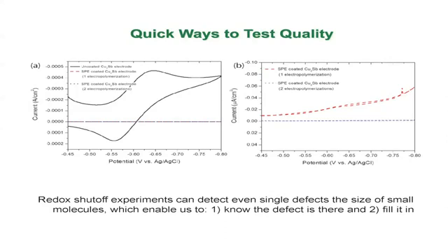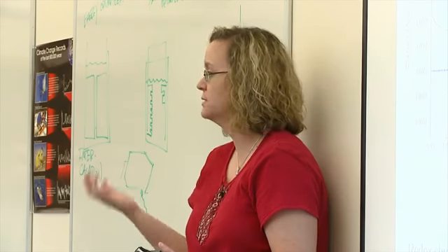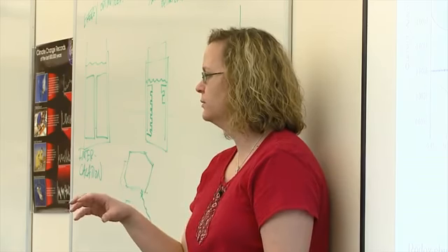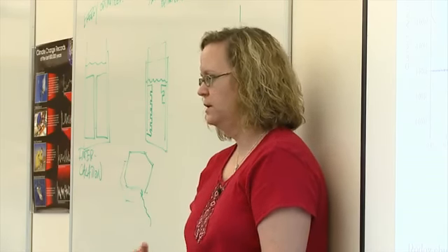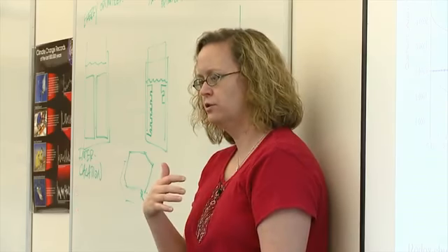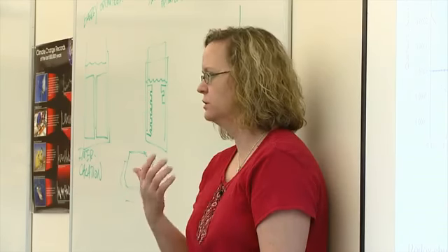This is one of the dumb things that I thought was my most clever idea ever, but if I had talked to an old electrochemist, they would have told me that this was an obvious thing to do, but it just had never been used in this field before. So here's the idea. You have this huge structure with all the surface area, and you cannot possibly check it all optically or with an electron microscope. So we wanted a way to know, is there one mistake just somewhere? We don't care where, we just want to know that it's there or not. So what we do is we take a small molecule that has really well-behaved electrochemistry. And when you scan in voltage and you measure current, you get this really typical shape that's often called a duck shape.